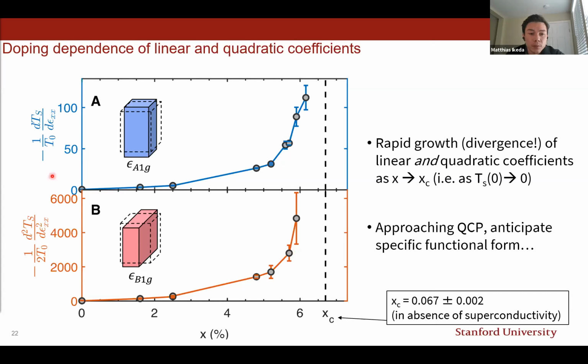As you can see, indeed, both of these coefficients increase drastically as we approach a critical composition as determined from a high magnetic field experiment in the absence of superconductivity. Now, if we were to approach a quantum critical point, we would expect a particular functional form of these coefficients. As you can see, however, the data density and error bars do not allow us to actually extract this power law from this data. I would like to show you, however, how we were still able to find the power law in this data.